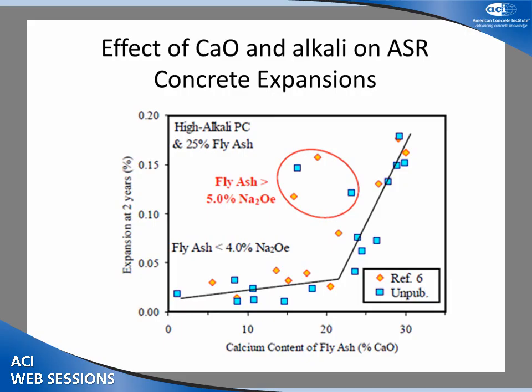And then there are cases where you've got a really high alkali content in the ash. These ones are all over 5% equivalent alkali. But even at a lower calcium, you can have some issues, which is why we have the secondary limit on the alkali in the ash.